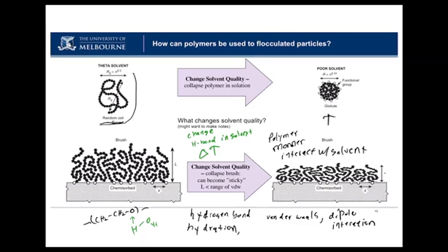And there's problems where this becomes a problem if you're trying to break the steric stabilization. You might actually start thinking about this. Sometimes though, people actually want polymer brushes that are very robust in high salt conditions, particularly if you're trying to put particles or keep particles stable in things like reservoirs or high salinity oil recovery. You actually might want things to be stable. But changing solvent quality, changing hydrogen bonding, the polarity of the solvent, its dipole moment, changing temperature, adding salt are all things that can change the solvent quality.